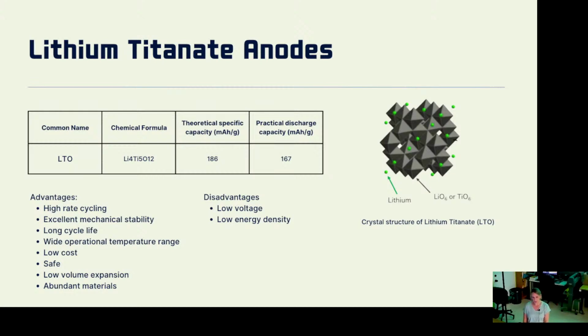But when I found out that these anodes can do like 30 C cycle rate, super fast, and they're super stable, and they're amazing across a really wide voltage range, and they can cycle for not just thousands of cycles, but tens of thousands of cycles. Amazing. And I just talked to somebody who said one of the really tough experiments in batteries is to do 3 electrode cell experiments. And he said that using lithium titanate as a reference electrode is sometimes more beneficial than lithium metal because it's so stable. That just blew my mind, but that makes complete sense.